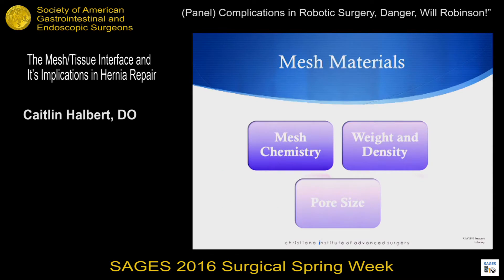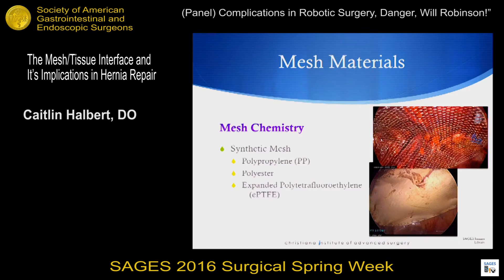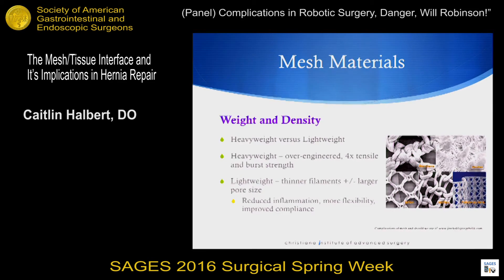The three things I'm going to be talking about as far as the mesh itself and the makeup of that mesh is not only the chemistry of the mesh — so is it polypropylene, is it polyester — but what's the density, and why is pore size important? I'm going to be specifically talking about synthetic mesh. The expanded PTFE — I'm going to be talking about that laminar version, but also the monofilament knit version, which really acts like a large pore mesh. The density of a mesh is related to the surface area that affects the tissue, so the more material in contact with the tissues will affect the inflammatory response and ultimately the tissue integration.